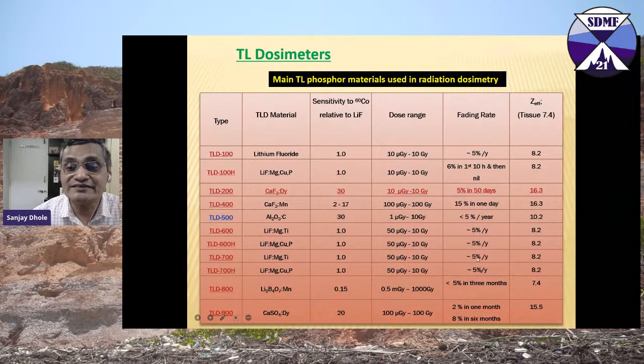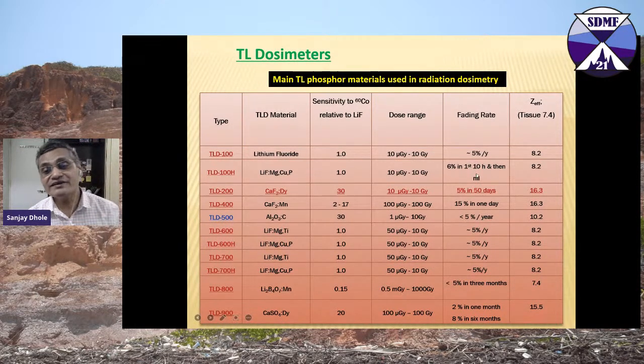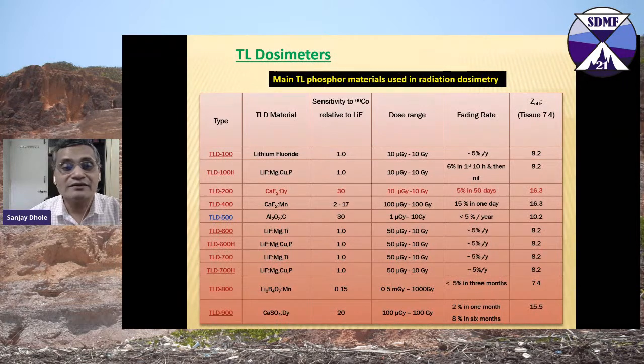And their fading rate is also given. On an average, the fading rate comes around to be 5% per year, and that is extremely good. And all of them require Z effective, because your tissue, if you look at it, the tissue or adipose, contains mostly water, and water has a Z effective of 7.4. So all of them are close except TLD-200 and TLD-400, that is calcium fluoride dysprosium and calcium fluoride manganese, which is 16.3. Others are very close to tissue equivalence, that is 8.2.